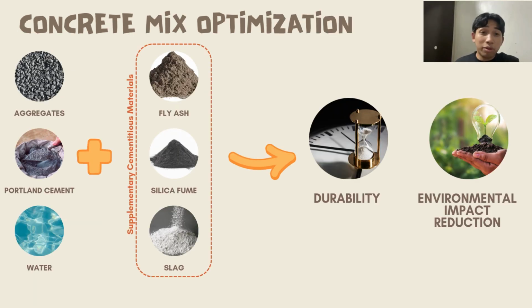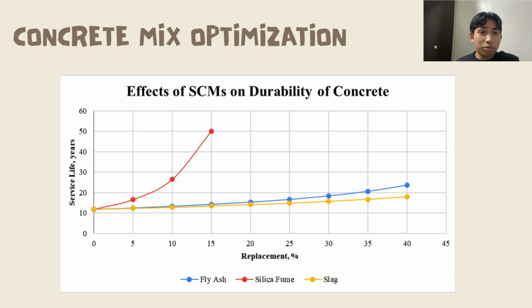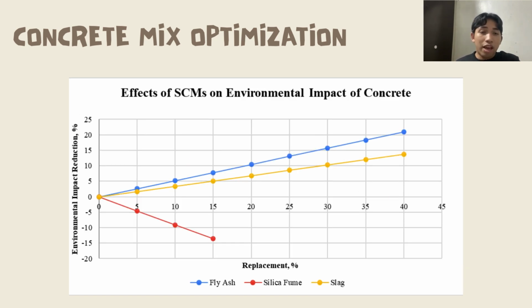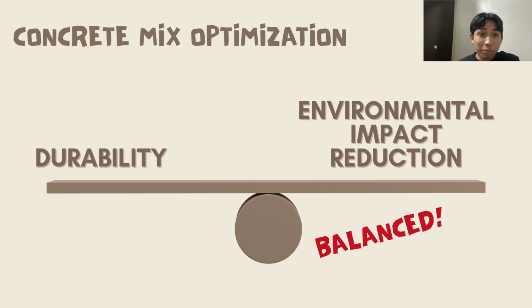The team wants to optimize a mix containing the SCMs shown while considering their effects on both durability and environmental impact. In terms of durability, it was found that silica fume produced the most durable concrete even at a low replacement percentage, followed by fly ash and then slag. In terms of environmental impact, fly ash produced the most eco-friendly concrete while silica fume yielded negative results. Again, we want a mix that balances both durability and environmental impact reduction.